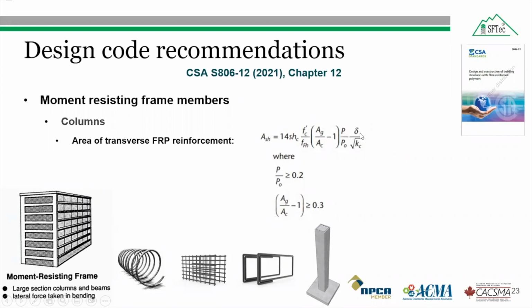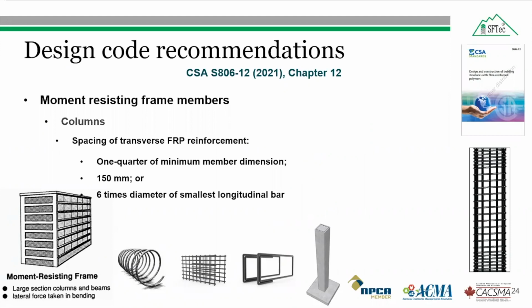And the delta you can see here is the design lateral drift ratio, which is generally 4% for the moderate ductility requirement. And Kc is the confinement efficiency coefficient, which is generally taken as 1 for circular spiral or circular hoops. So the transverse FRP reinforcement should be spaced at a distance not exceeding the minimum of 1/4 of the minimum member dimension, 150 millimeter, and 6 times the diameter of the smallest longitudinal bar. The special moment resisting frame detailing of the transverse fiber reinforced polymer reinforcement should be provided in the plastic or most damaged region. So you can see here at the top and at the bottom, where the columns are generally connected, there you can find the most damaged region. That's why this special detailing should be provided at the ends.